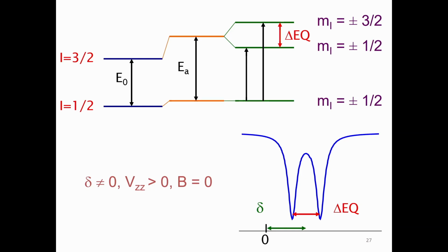Out of the valence, you have, for example, a network. You have your local probe. Around it, you have plenty of atoms, and you are looking now at this environment. That means, what I wanted to say is that here you have some asymmetry. In the case, for example, where the two lines are the same, there is no degeneracy. That means you have a cubic cell, cubic symmetry.